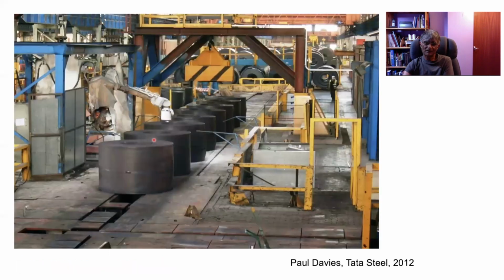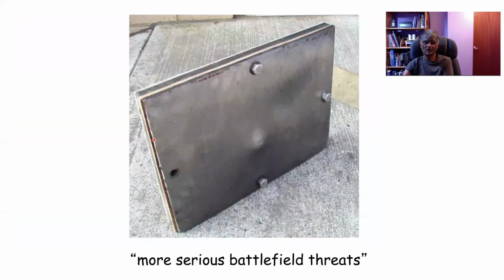And this is the mass production of the material. Now, of course, these coils are not the nanostructured bainite because you would not be able to uncoil them. It's so strong. So they're produced in the pearlitic condition, and then it will be sliced up and heat treated to obtain the right structure for the components. And this is an armor test.